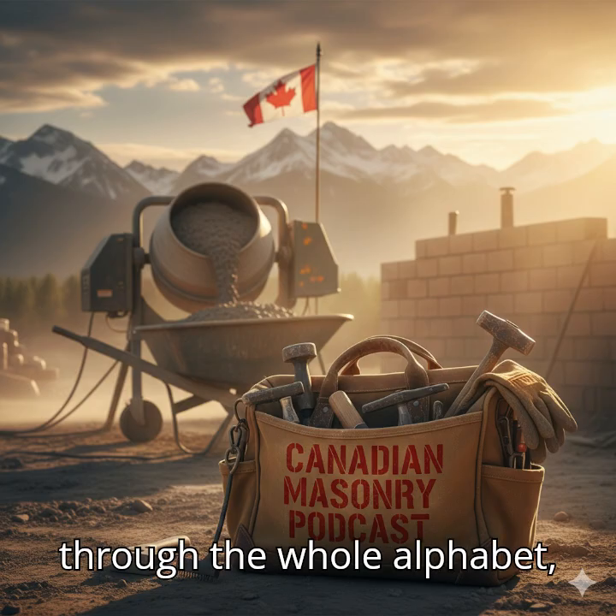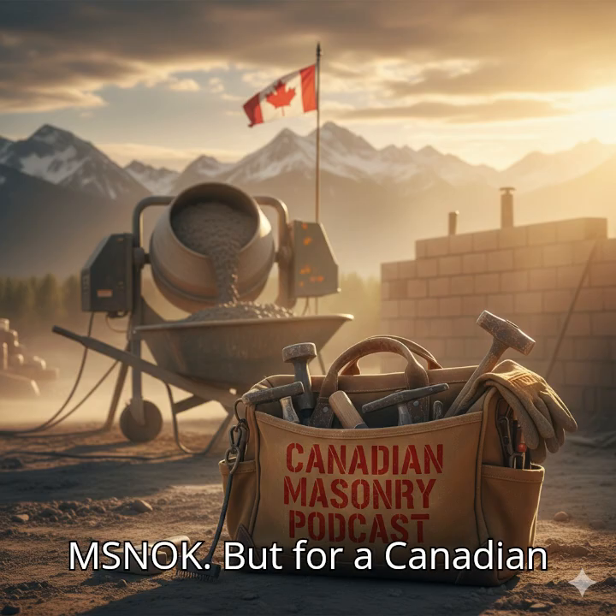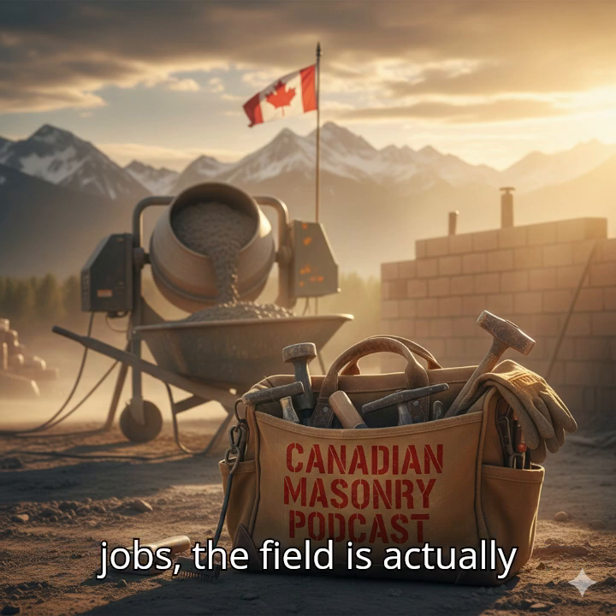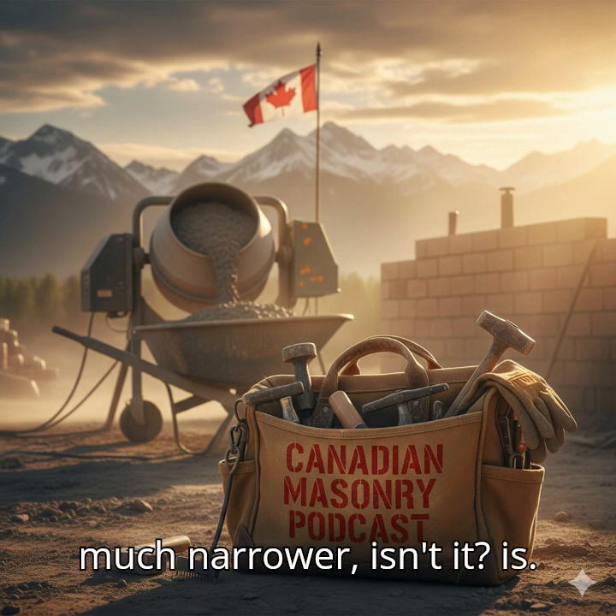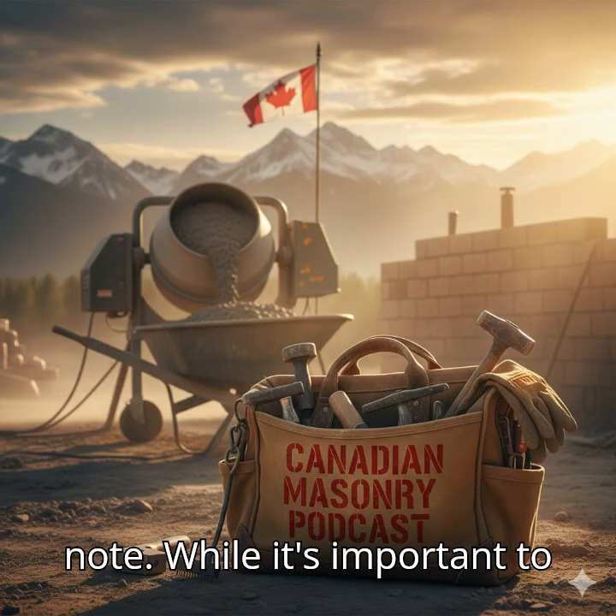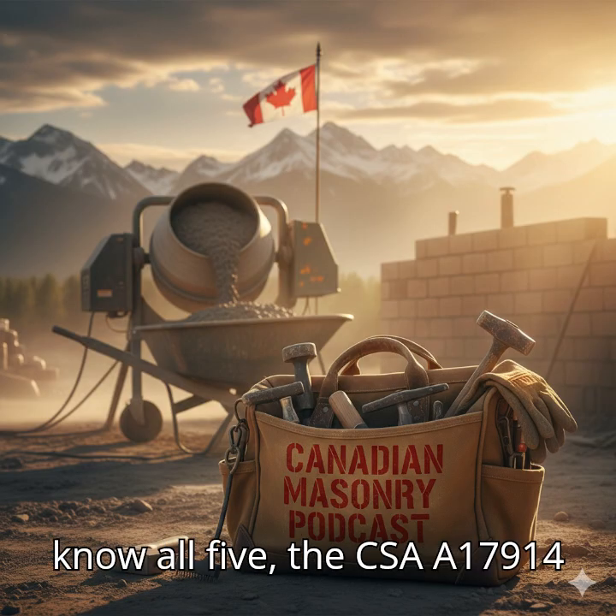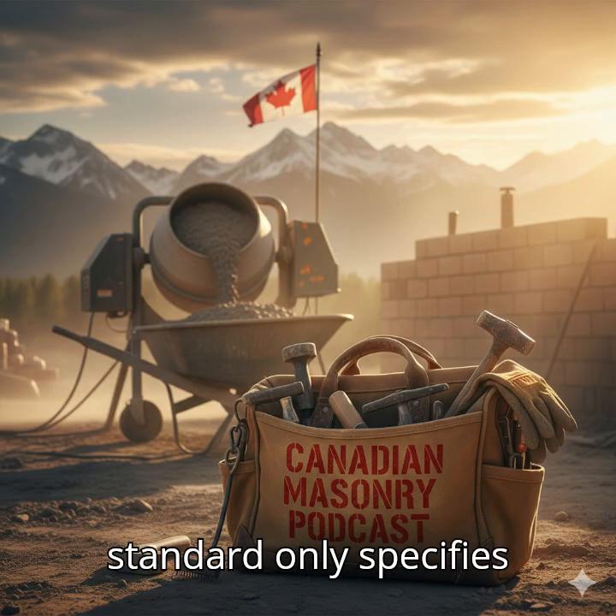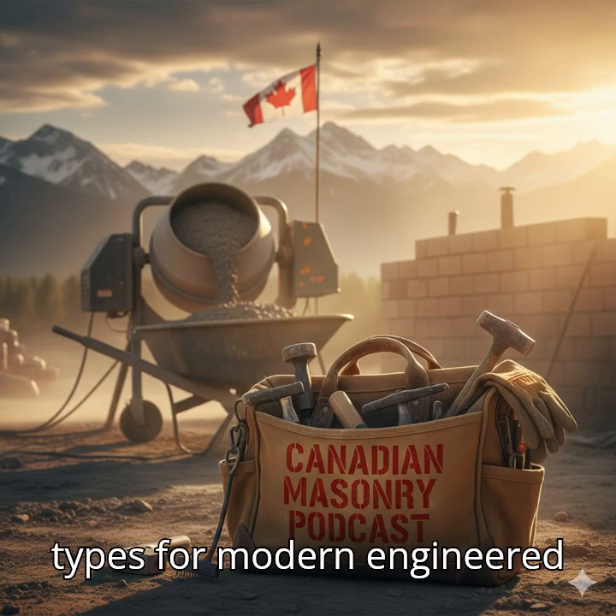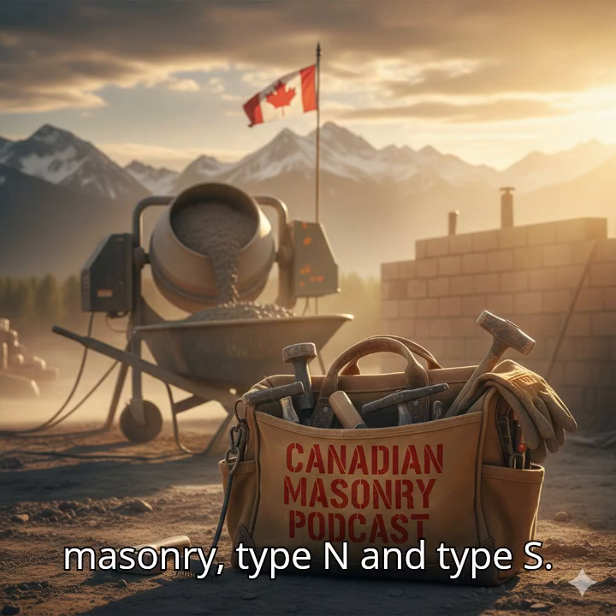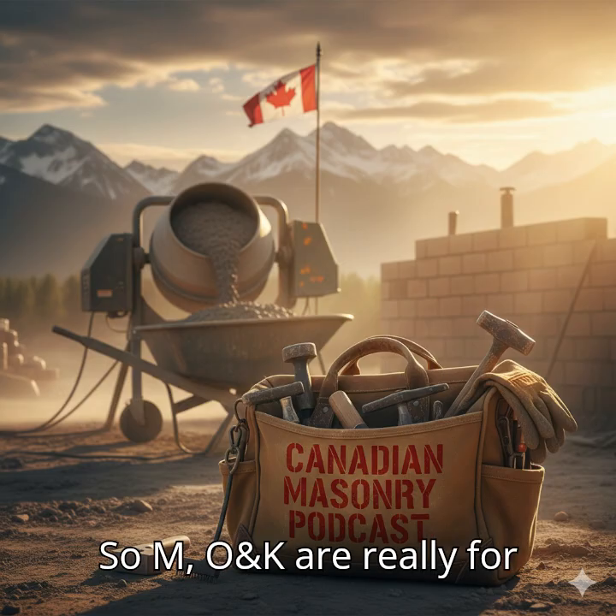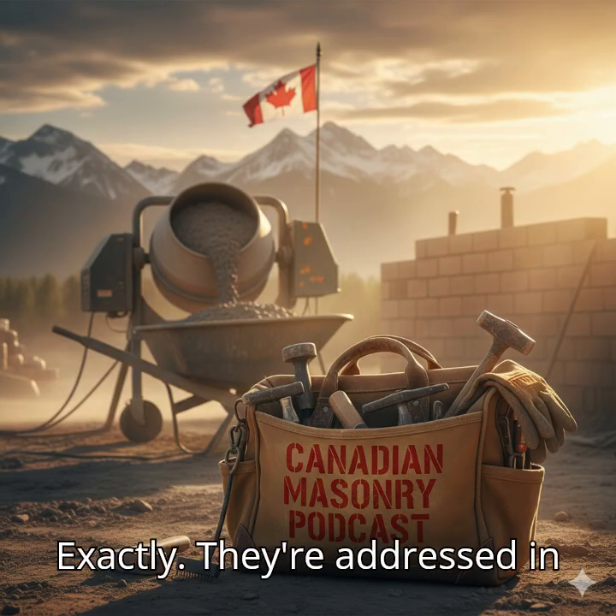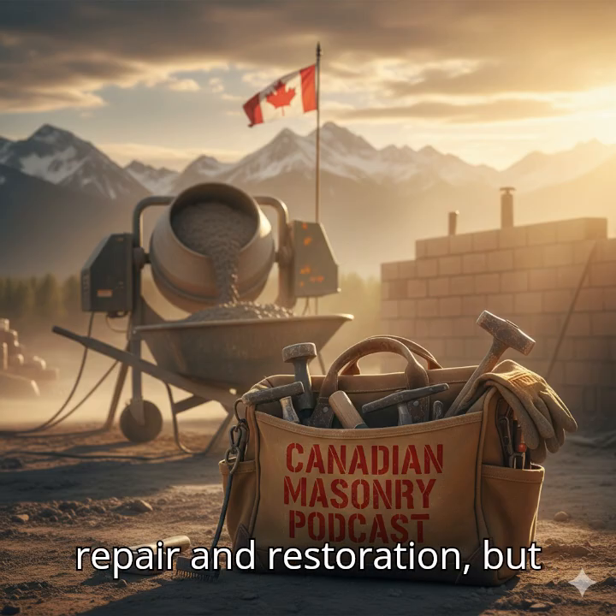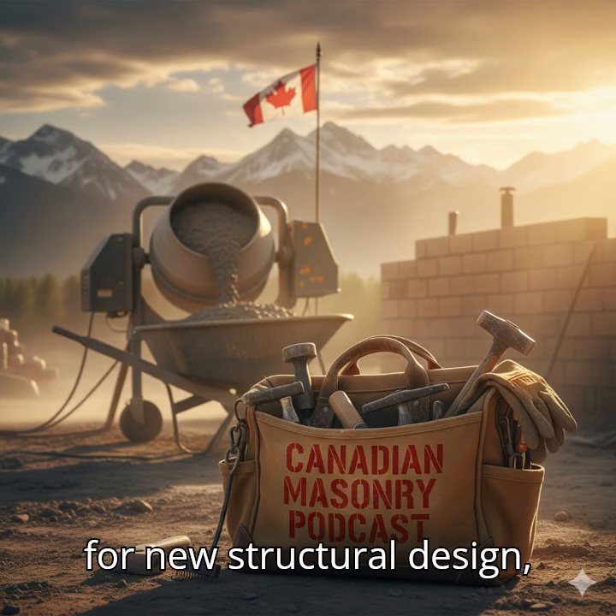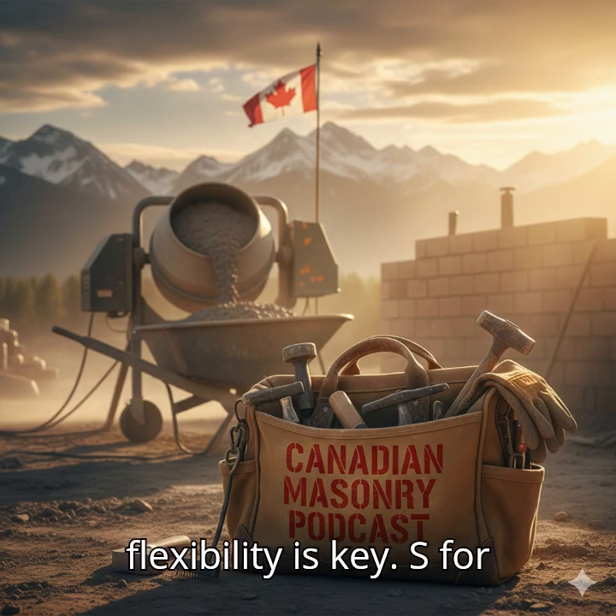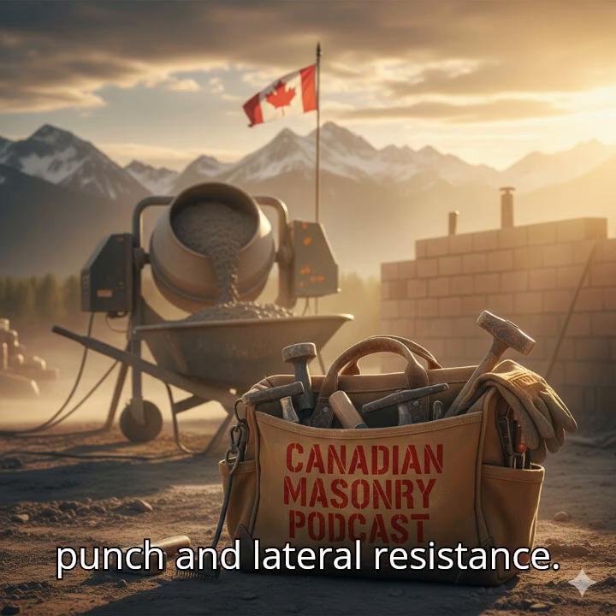So we've run through the whole alphabet, MSNOK. But for a Canadian apprentice working on modern jobs, the field is actually much narrower, isn't it? It is. This is a critical regulatory note. Right. While it's important to know all 5, the CSA A179 standard only specifies detailed requirements for 2 types for modern engineered masonry, Type N and Type S. So M, O, and K are really for specialty situations. Exactly. They're addressed in annexes for things like repair and restoration, but for new structural design, it's all about N and S, for general use, where flexibility is key. S for when you need that structural punch and lateral resistance.